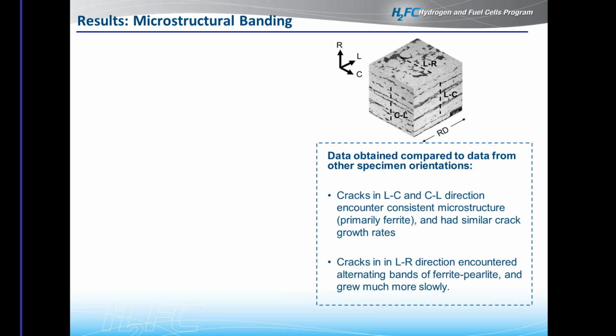And so even though this is a ferrite pearlite steel, the fact that it is banded gives us the capability to test the material in different orientations. In other words, we propagate the crack through the microstructure, for instance in the CL and LC orientations. These dashed lines represent the crack plane. You can see that they're encountering the same microstructure as they propagate through that cube of microstructure. They're essentially parallel planes of ferrite and pearlite, and so maybe they're going to behave similarly. That's what we would anticipate.